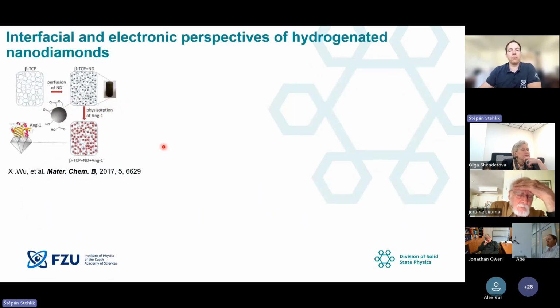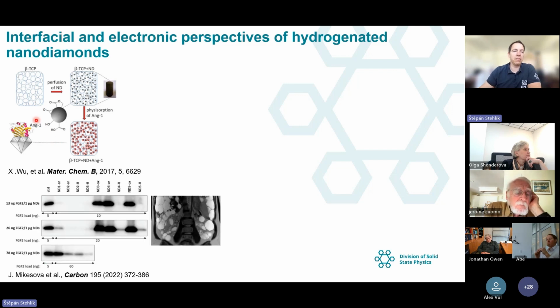I also want to point out that this positive zeta potential, and the hydrogenated nanodiamonds overall, are quite perspective in some applications. Their positive surface charge can immobilize some biologically relevant proteins. It can also remove fibroblast growth factors, for example, because there is a strong affinity of the fibroblast growth factors towards the hydrogenated nanodiamonds. So it can be used in therapy of some diseases where this FGF expression is too high.